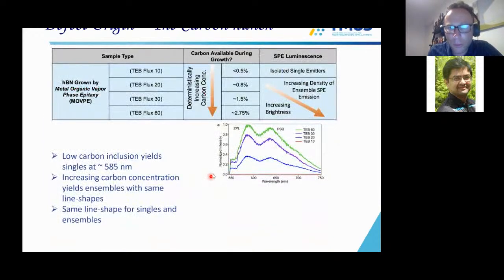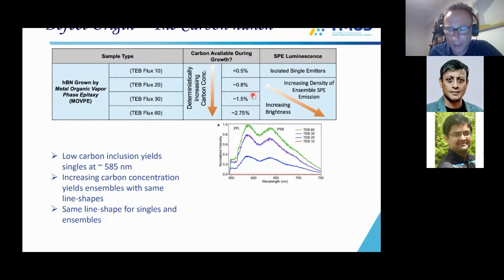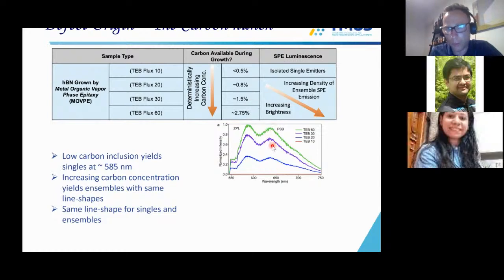And so this increase in luminescence is actually important. So you can see it here. As we went from basically 0.5%, we saw almost no emission. And as you increase your carbon doping in the growth to, let's say, about 1.5%, you can see this beautiful line shape, which resembles our emitters. And it's important because you can increase it linearly or controllably with the doping of carbon.